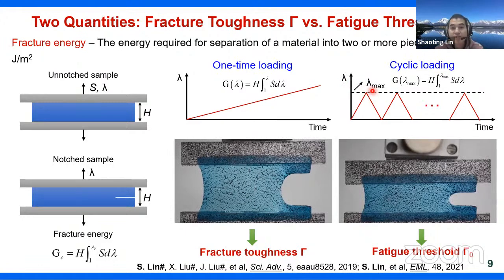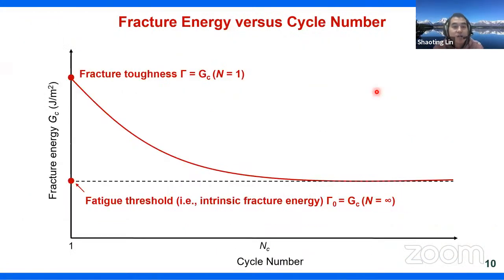These two quantities can also be understood by this plot. Let's do an imaginary experiment. We have many samples. Each sample will experience cyclic preconditioning with a controlled cycle number. The fracture energy measured under the first cycle is the fracture toughness, gamma. The fracture energy is likely to gradually decrease and eventually reach a steady-state value. This steady-state value of the fracture energy is the fatigue threshold of the material, which is also named the intrinsic fracture energy of the material.